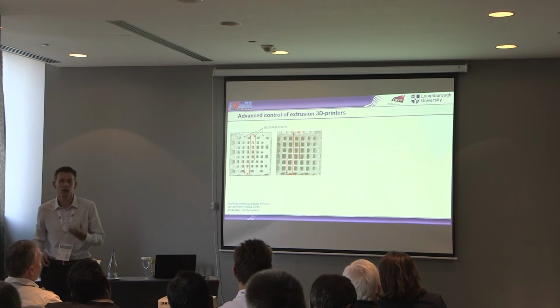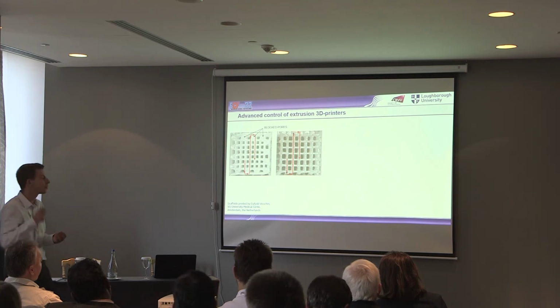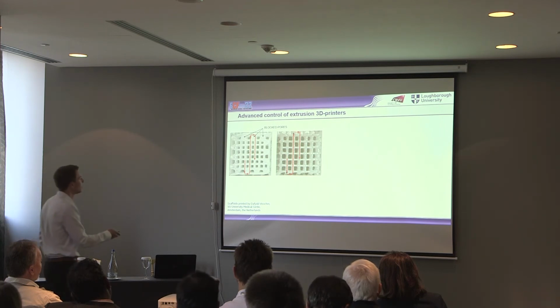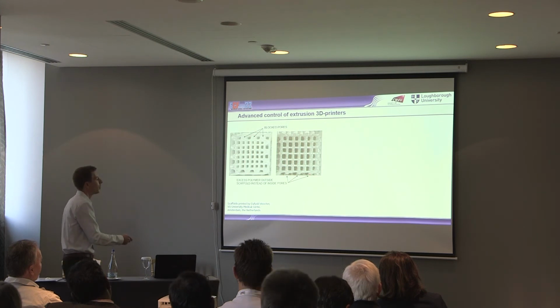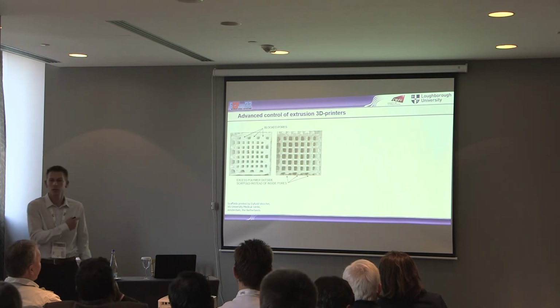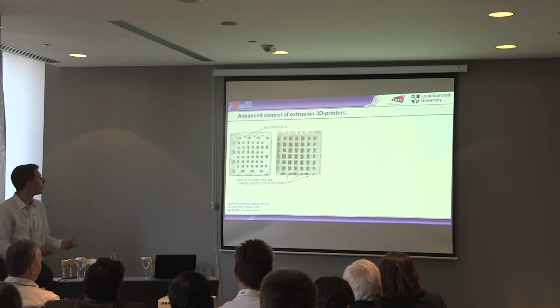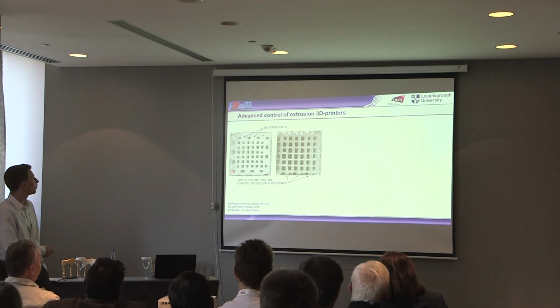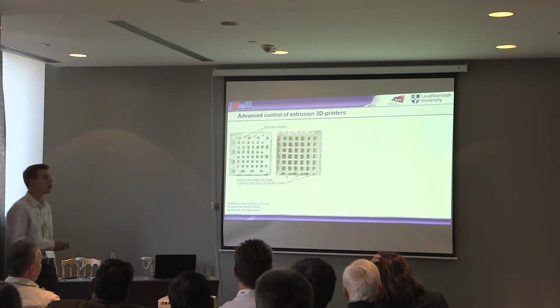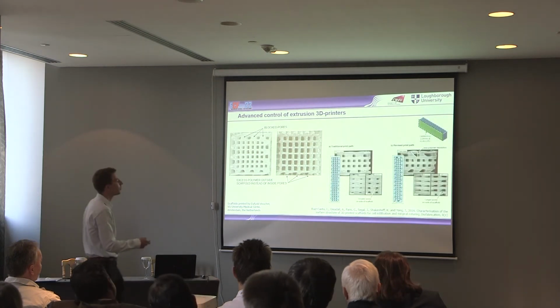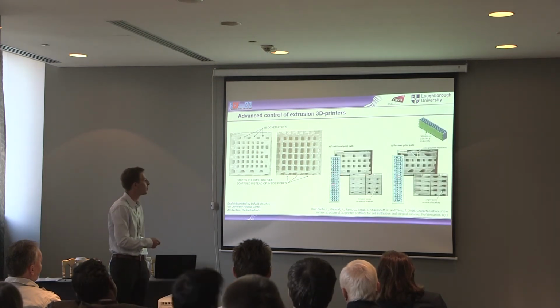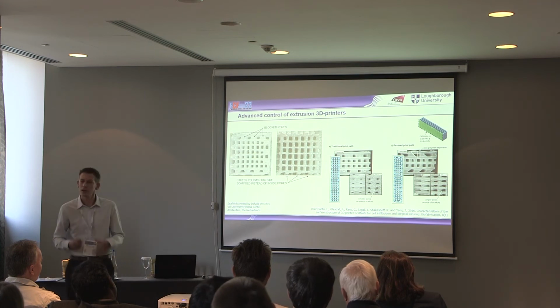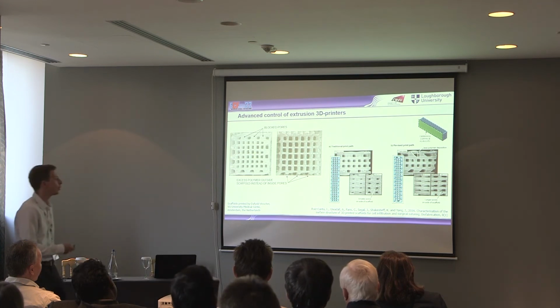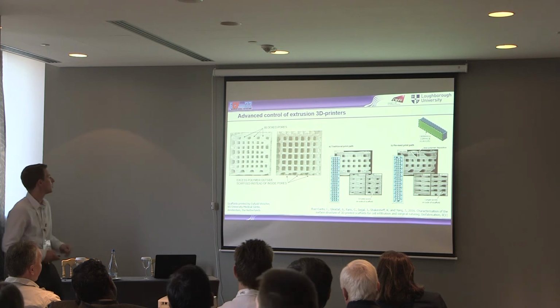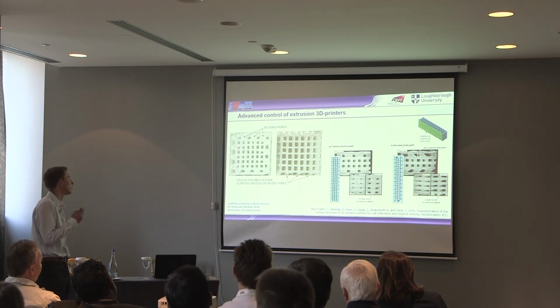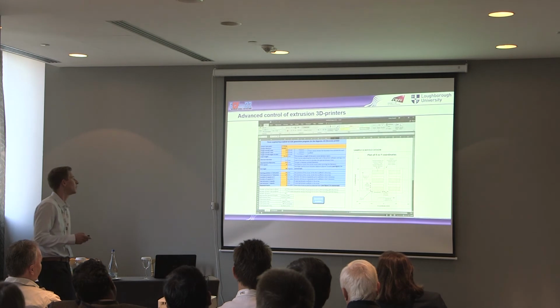And all that does then is that excess polymer, we can't just switch it off and tell it not to print, is being dumped on the outside of our scaffold rather than inside, which was important for this work because they wanted to have consistent pores throughout the whole scaffold rather than inconsistent changes. Then it was similar things for other scaffolds as well. Instead of coming right to the end, cut the corners, and that means you get nice pores on the surface because this was about infiltrating these polymers with hydrogels and cell seeding.